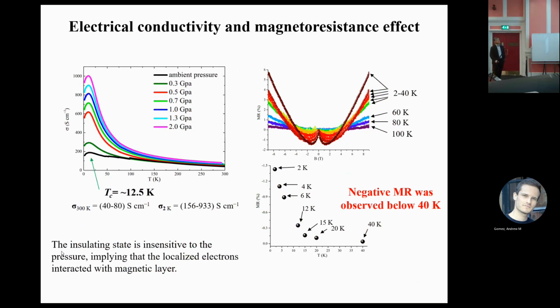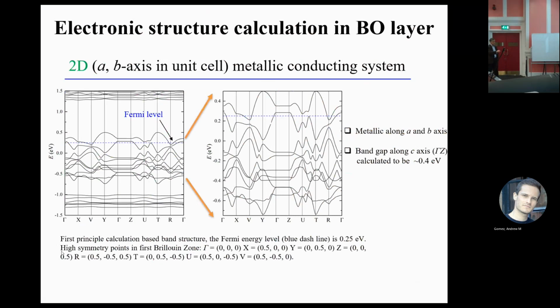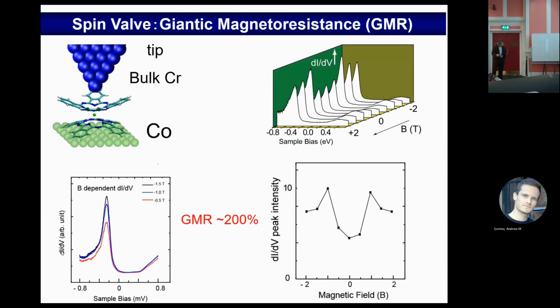So every time we observe the negative magnetoresistance. So this is a band calculation. Actually, the Fermi level is cutting, so this is actually metallic. So then we must realize giant magnetoresistance. So then we use a spin valve, cobalt substrate, single magnet, chromium tips. So at 0 Tesla, 5, at 1 Tesla, 10, twice. This means 200%. Finally, we realize giant magnetoresistance.